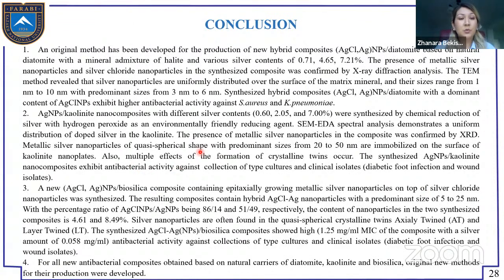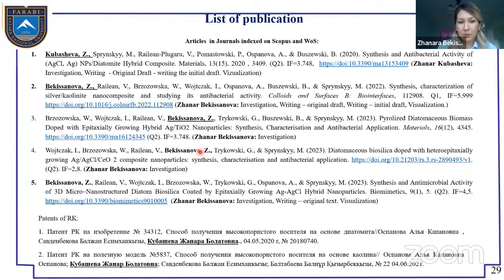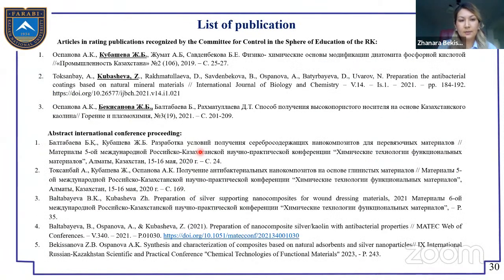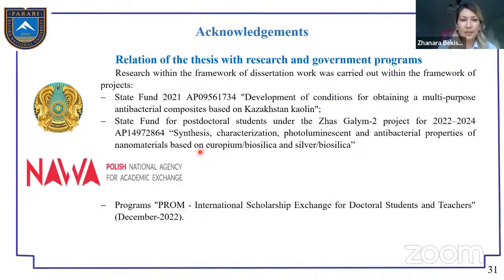And third, new hybrid nanoparticles based on diatomaceous biosilica with epitaxial growth were synthesized with 2 concentrations and with a predominant size from 5 to 25 nanometers, and show high antibacterial efficiency with a minimum inhibitory concentration of 1.25 milligrams per milliliter. And for all the new antibacterial composites obtained based on natural carriers, diatomite, kaolinite, and biosilica, productions were developed. And a list of publications in Scopus, patents, and articles, abstracts in international conference proceedings, and